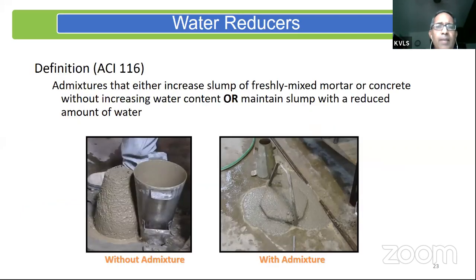So let me just quickly take a look at what are some of the admixtures that are used. The most common admixture that has now become quite common in usage is the water reducer. It basically reduces the demand for water. And what that does is, by adding a little bit of this water reducer, I'm able to increase the flow of concrete, and basically get concrete to flow instead of slump. So this is how concrete looks when it slumps. It basically still retains the shape of the cone, but when it flows, it basically spreads. And that's what I'm trying to achieve.